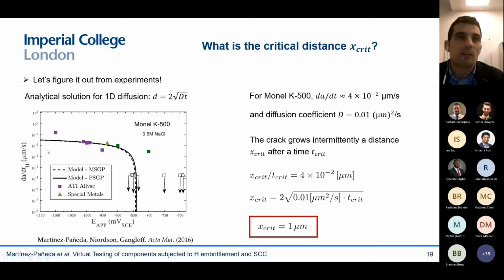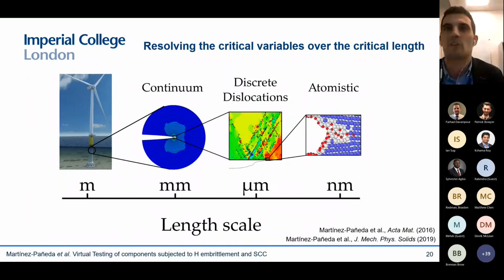And then we do an experiment, and we can see this is the crack speed for different applied potential. This is taken from one of our papers. This is a nickel superalloy. And for example, if we take these 3 replicate experiments here, we get a crack speed of 0.04 microns per second. Since we know the diffusion coefficient of the material, we can measure it. Then we can take into account this and the crack speed, and that gives us 2 equations. And by substituting, we get a critical distance of 1 micron. So this is roughly what you would expect, a critical distance of a few microns ahead of the crack tip. So that is the critical distance of our problem.